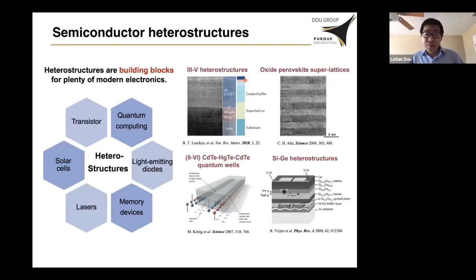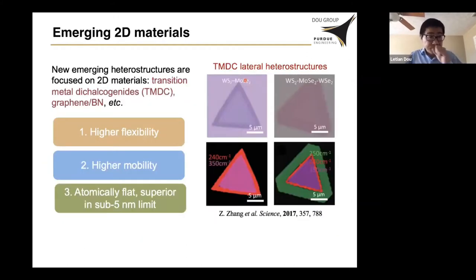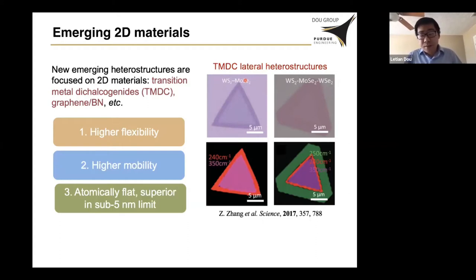To further improve device performance and decrease device size, new materials are needed. Recently, 2D materials have attracted a lot of attention, such as transition metal dichalcogenides, because of several advantages. For example, they are structurally tunable and have relatively very high charge carrier mobility, even at the nanometer scale. For traditional semiconductors such as silicon, the charge carrier mobility decreases a lot if you shrink the size below 5 nanometers. But 2D materials can still sustain very high mobility even at the one-nanometer regime. So there are lots of promising features for 2D materials and lots of progress has been made.